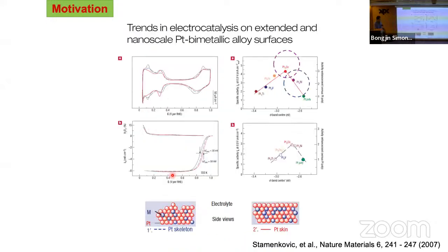So they tested basically a series of the 3D transition metal families: titanium, vanadium, iron, cobalt, nickel, and this pure platinum. They characterize this with electrochemical measurement. Here, they characterize this material according to the so-called d-band center, which is the electronic structure. They compared that with the series of the electrochemistry reactions. They saw this platinum cobalt shows actually the highest reactions, and also platinum nickel is actually very near.